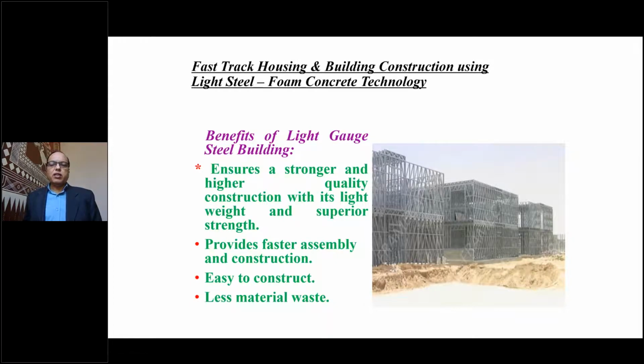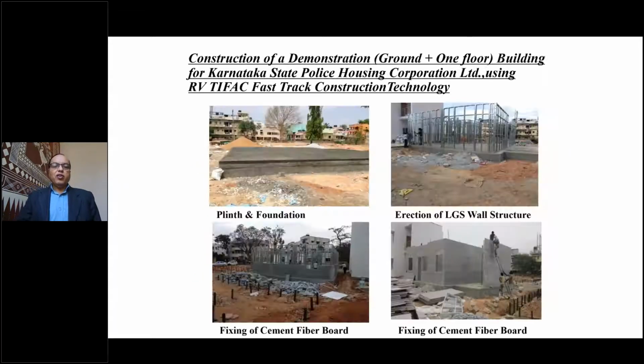Here, instead of in situ concrete or precast concrete, we have a light gauge steel frame. This light gauge steel frame can be assembled in any place very easily, and with that, the structure is made. On either side of the wall, you put composite boards and pour foam concrete into that. Once you pour foam concrete, the composite boards also stay in place, not that you will remove that shuttering. That shuttering also remains as a part of the construction.